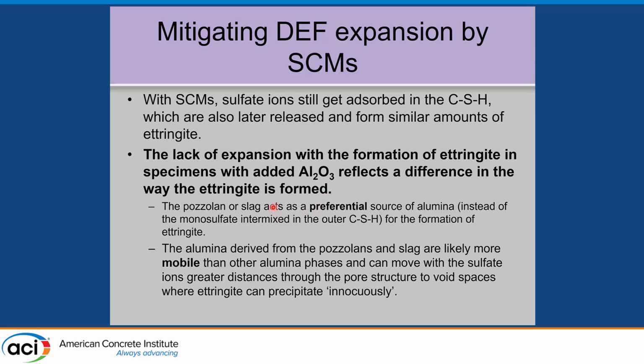So the pozzolan or slag acts as a preferential source of alumina to react with the sulfate to form the ettringite, instead of the monosulfate that's intermixed in that CSH. So instead of turning monosulfate into ettringite, which can be expansive, it forms ettringite elsewhere where the pozzolans are, moving the alumina from the pozzolans and the sulfate to open spaces where they form. So the ettringite's still forming, but it's forming in places where there is no expansion.